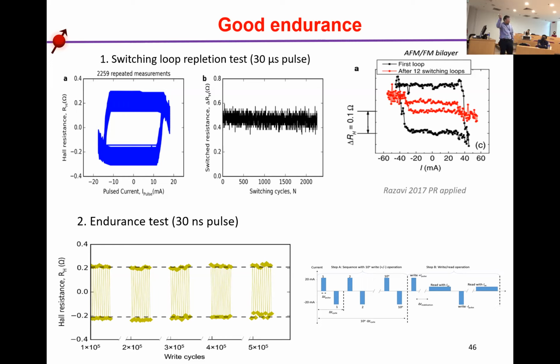It took one month because of 2 minutes for each loop. We have also demonstrated up to 10 to the power 5 cycles. Yes, something broke, but it was not the device, it was the electrode, broken because of large contact resistance.